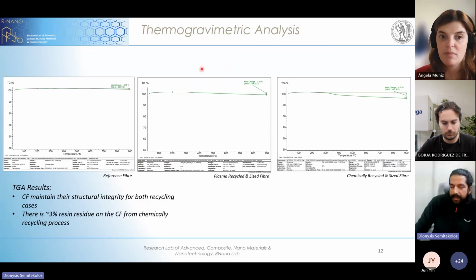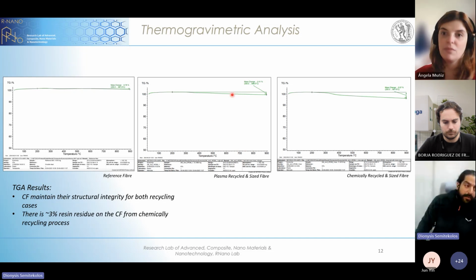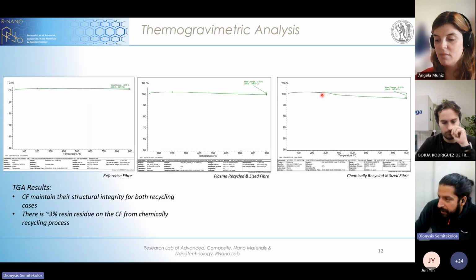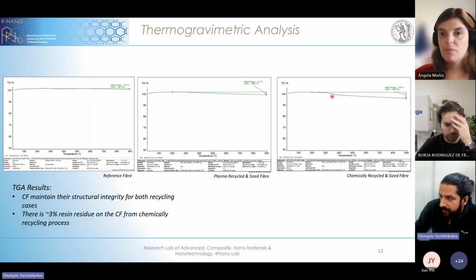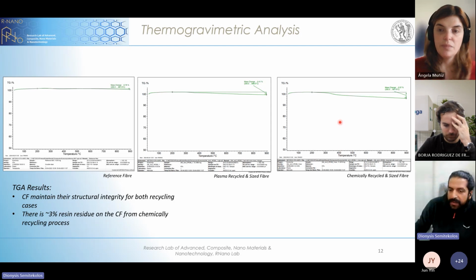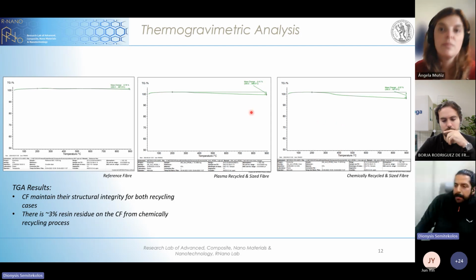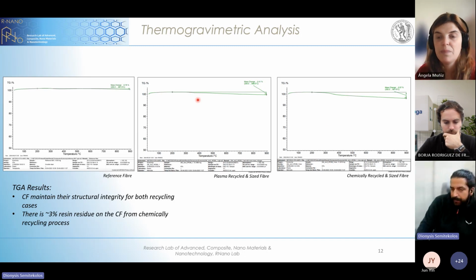So moving forward, we wanted to assess the structural integrity of the fiber after the solvolysis. If we noticed any considerable decrease in the weight after, I don't know, 600 or 700 degrees, then this would mean that the solvolysis process affects the structural properties of the fibers. And this is not the case here. We only see some slight decrease, approximately in the range of 250 to 400 Celsius, which is related with the removal of the sizing that we apply or any resin residue on the surface.